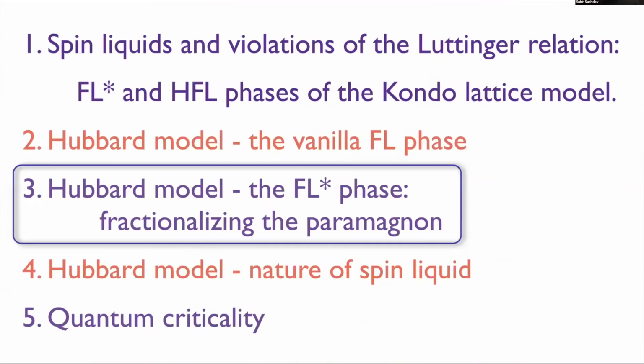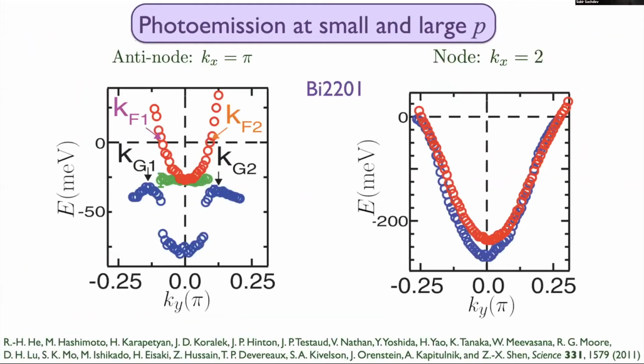Okay. So then when you lower the temperature, you ignore the green line, you get this dispersion here, which has got a gap-like feature. So this is the electron excitations below zero energy right here. So that's the pseudo gap right there. And this is not related to superconductivity. The green line is related to superconductivity in some way. And an important point here, which Patrick Lee has particularly emphasized, is that the maximum of this dispersion here, this gap, occurs at a different momentum than the Fermi surface point here. And so to explain that, Patrick Lee has postulated a pair density wave. I'm not going to use that approach.